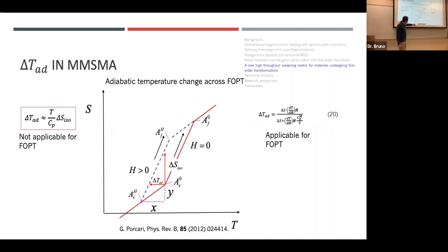So there's been some work by an Italian group, Porcari, where they quantified the adiabatic temperature change across a first-order structural phase transformation by using, it's very empirical, they just use the entropy versus temperature diagram and use some similar triangles to come up with this empirical expression. I've actually measured the adiabatic temperature change in these materials and then computed it with both methods across a magnetostructural transition. And the empirical method definitely works a lot better. So I use this metric in my performance metric.